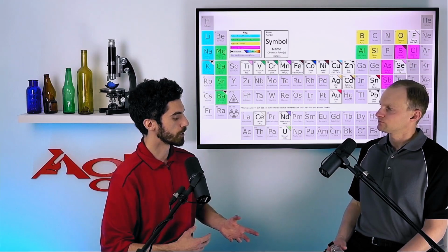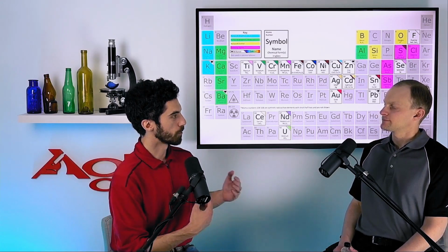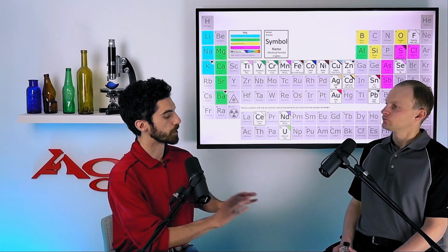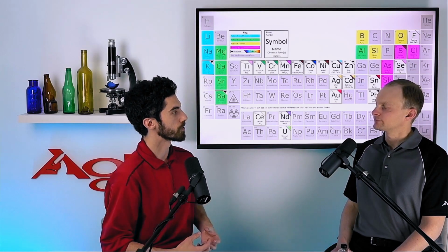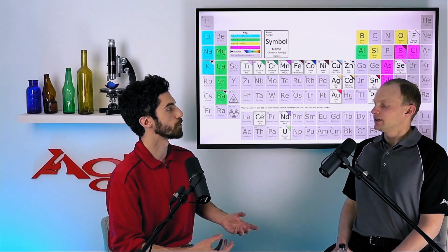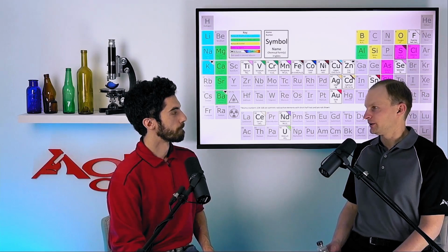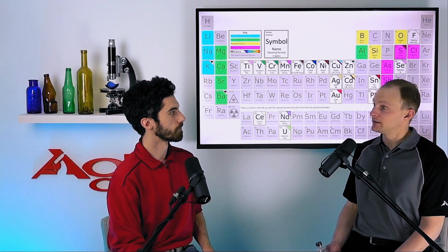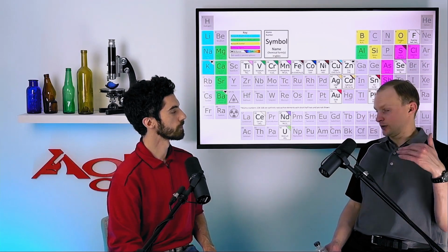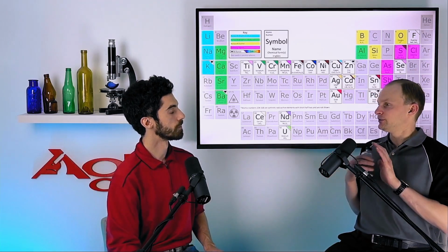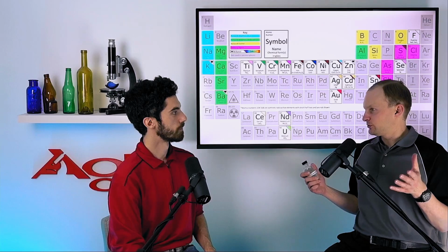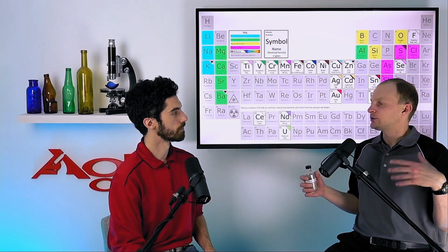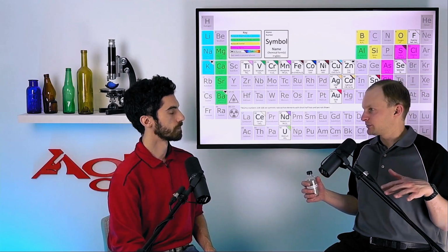So when we use this, obviously we're going to need to lower maybe a little bit of the silica and the calcium in other areas so we can introduce this Calumite slag, right? Because we're introducing all three of them, but we're specifically looking mostly for that alumina. Now, what does this do for us in terms of the glass making process? When we add alumina, what does it do? Well, adding alumina actually makes glass harder to melt and can raise the amount of energy that you need to make the glass. So this is one of the reasons why, even though more alumina is in some senses better, making the glass more durable and giving it certain other properties, typically we aren't going to go too high, because we don't want to increase the amount of energy and decrease the workability of that particular glass.